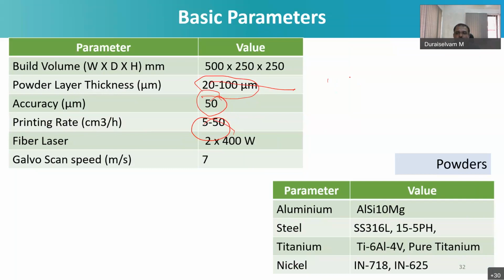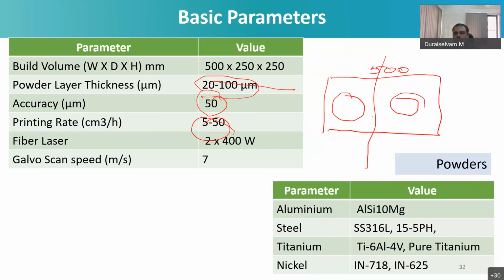For example, when you look at here, this is the build platform, and this is 500 mm, and this 500 mm is being divided into 2 portions. One laser will cover this portion and another laser will cover this portion. If you have a big part covering the entire build area, both the lasers will simultaneously operate and print the entire part. And if you have a number of small parts, some parts that you can locate here, some parts that you can locate here, you can simultaneously print in order to save printing time, because most of the time the printing speeds are very slow, and you need to use this kind of a strategy in order to improve the printing capability.